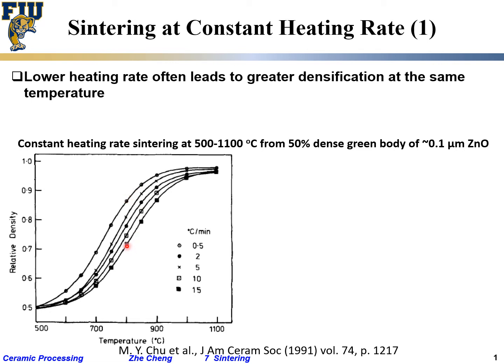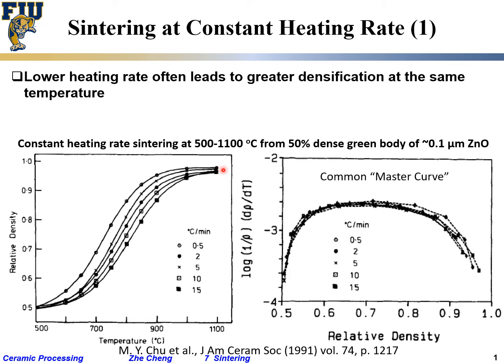When you heat too fast and reach a target temperature, the material has not accumulated a lot of heat, so it is at lower density. This is constant heating rate — you just ramp it up. Eventually, if you reach a high enough temperature, all the curves would be more or less close, because at sufficient temperature the heating history matters less.